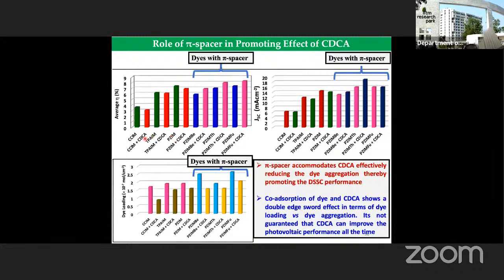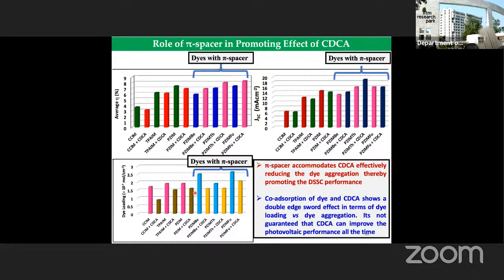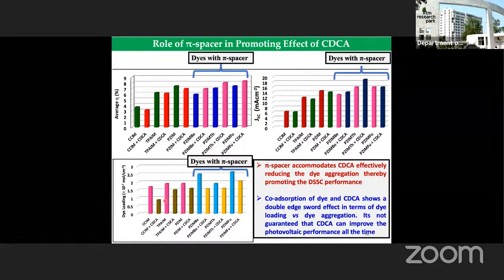With that, if you add CDCA, what happens is the power conversion efficiency goes down. Compared to all the green bars, the red bars are at lower efficiency. It goes down. Why is it going down? If you look carefully, the JSC also is going down for those three cases. Also, the VOC and dye loading also go down. So all these are contributing to lower performance of the dye.